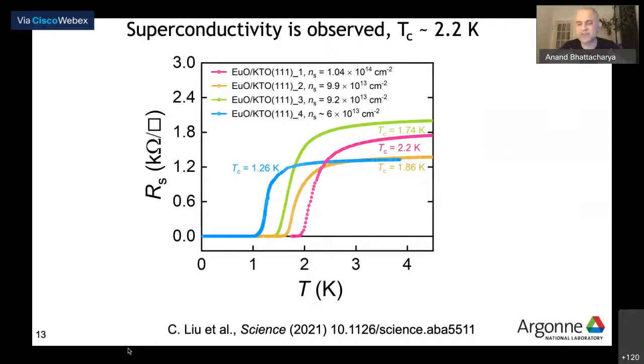We saw this first. We saw superconductivity. Then we did all these checks, and the superconductivity is very interesting. It's very robust. You notice there are fluctuations, so there's an enhancement of conductivity out to even beyond 4 Kelvin. In fact, we see it up to like 10 Kelvin in some samples. That's how we guessed it was superconducting. We don't always measure our samples in a dilution fridge. We guessed there was superconductivity initially and then looked harder and we found it.